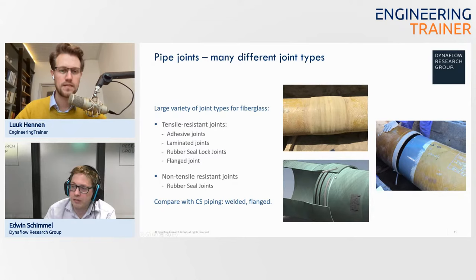So if you have a locking ring, then the locking part is really the weakest part of the piping, but it's mainly in large bore piping that it's often used, which is often underground, and then you don't load the pipe with the locking ring to the maximum pressure because the soil resists it.